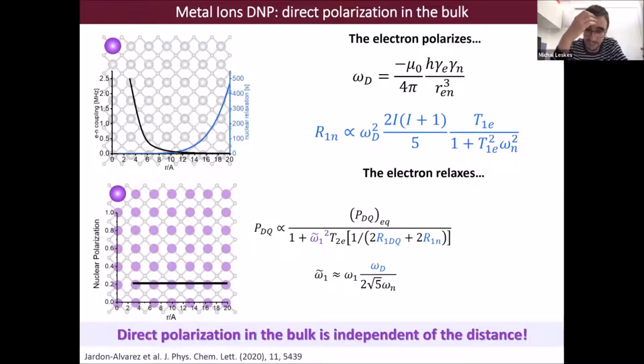relaxation. And this result has huge consequences for us, because it ultimately means that we are able to hyperpolarize the entire volume of the sample in a homogeneous way, and therefore we will be able to continue getting quantitative spectra. And this all without the need of spin diffusion. And this is the explanation why we are able to get such large enhancement for nuclei such as oxygen-17 at natural abundance.